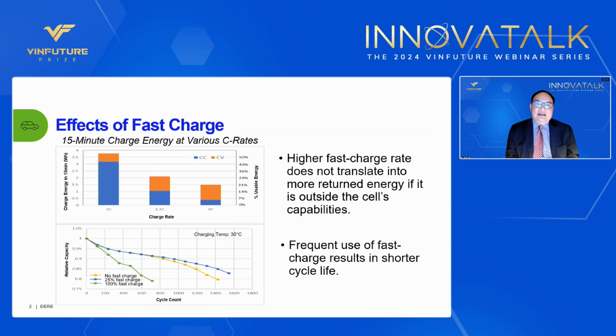So you can see here, the higher fast charge rate does not translate into more returned energy if it is outside the cell's capability. The plot clearly says that for a 2C rate, you get almost half of the energy back compared to a 3.2C rate and a 4C rate. So that's what it means in the top chart. The second plot on the bottom, I try to show you the effect of fast charge relevant to cycle life. And you can see clearly there are 3 plots, one with no fast charge, one with 25% fast charge, one with 100% fast charge at room temperature. And you can see the frequent use of fast charge results in shorter cycle life. Very clear.